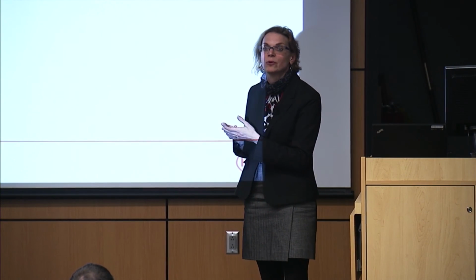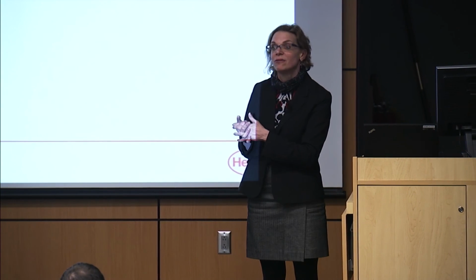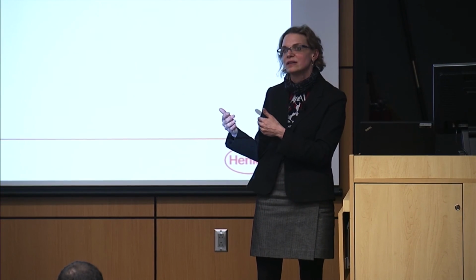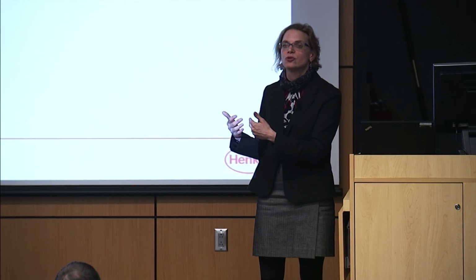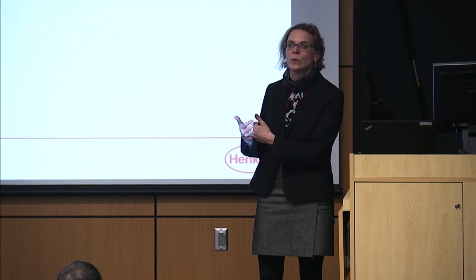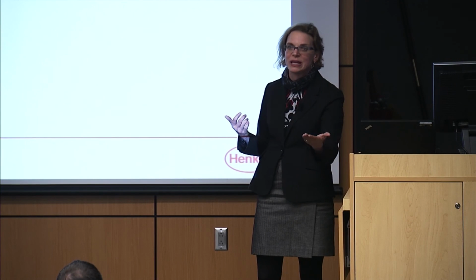So we want to balance oxidation or changing of the surface with the mechanical properties of the surface, and we also want to make sure that any oxidation or changes we do to the surface are positive for the lubrication condition. Anti-wear additives are very typical of this. This would be your zinc dialkyl dithiophosphate. And the idea behind them is to literally corrode the surface. You're oxidizing, you're phosphatizing the surface, creating a zinc deposit, but you want it to be controlled, and you want to make sure that it's more wear resistant than the base metal that you're coating.